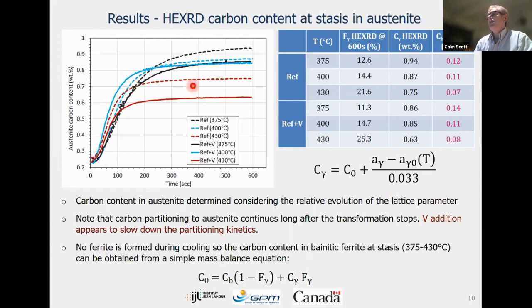The first thing is that the austenite, that's the retained austenite, is still being enriched in carbon long after the transformation is finished. So as I said, the transformation finishes about 180 seconds, you get to stasis, but we're still enriching the austenite in carbon, which is kind of interesting. Again, at the lower temperatures, here we've got a smaller austenite fraction, but we have a higher amount of enrichment in the austenite carbon content is higher, logically.